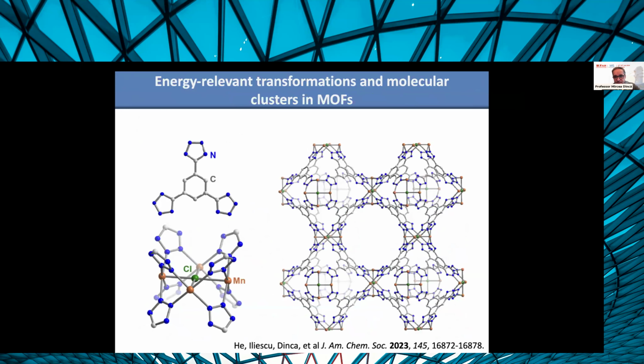So this site isolation, as I mentioned, will enable the formation of very reactive intermediates or even unique reactivity at the metal nodes. And the one example I'm going to tell you about is something we published very recently, but on a material that I actually made as a graduate student myself. And this was a very interesting material where the SBU is a manganese 4 cluster with a chloride in the middle between the 4 square planar manganese. So the chloride itself is actually kind of interesting. It's a square planar chloride. You don't see that every day.